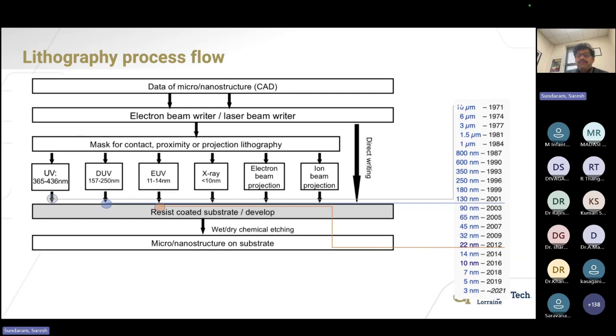Then we expose our resist with this source, and transfer the patterns of the micro or nanostructure into our substrates or our LED wafers, and then we realize them. Here you can see how, by changing the source of these lithography machines, we have reduced the pattern size and when we achieved it. In 1971, the microstructures were 10 micrometers in size, and for that we were using I and H lines. Then, using the same process, we changed to DUV, and the minimum feature size was 130 nanometers in 2001.